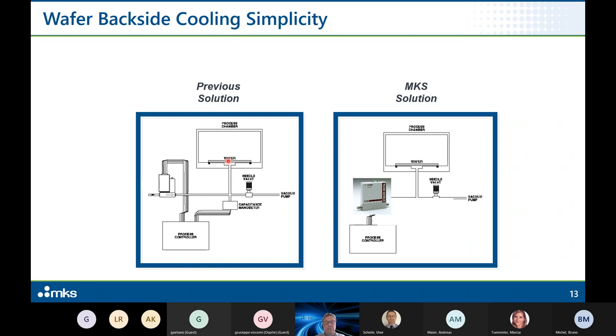If the pressure would be too low, then we have not enough helium atoms to remove the heat. And if the pressure would be too high, we would maybe blow the wafer into the process chamber, and it's end of process. So a tight control without overshooting is required here. Additionally, the helium flow is measured to check that the wafer is still in position and that there is no helium leaking into the process chamber.